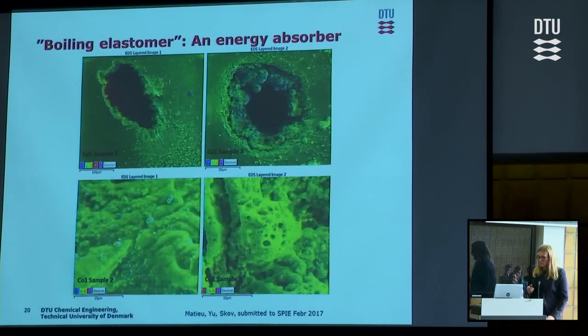We looked into that and wondered why it looked like this, and we have used labeling of the different components. We can see that after the breakdown in this zone we have a lot of boiling. We can see droplets forming here, so they are actually chloro-rich domains, and we are looking into how we can couple that to what is going on. But it means that this particular copolymer actually has the capability of taking up energy such that the energy is not dissipated out into the tear propagation.